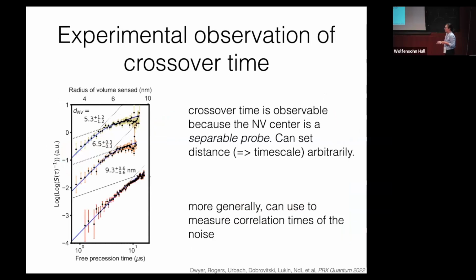All right. So armed with that theoretical model, what we can do is intentionally oversample a bunch of coherence decay curves, and we see this pretty nicely. We see this crossover time. We can independently measure the distance from the surface by doing proton NMR. So we do one of these coherence decay measurements and look for a little peak in the noise that comes from the Larmor precession of protons at the surface. We just put oil, and it doesn't really matter. But anyway, we get these independently measured depths, and it matches where this critical crossover time should be based on the distance very well.